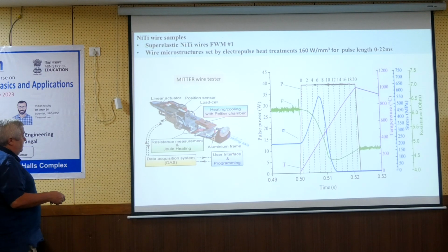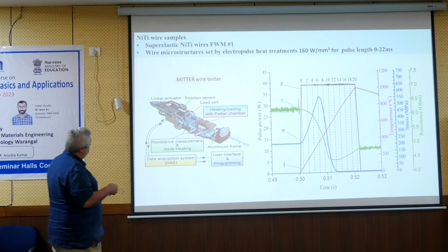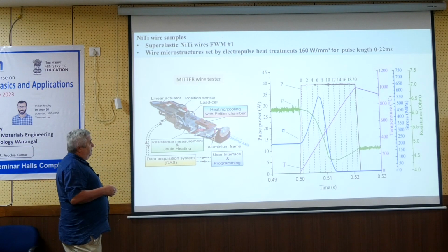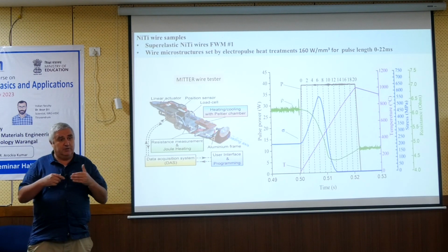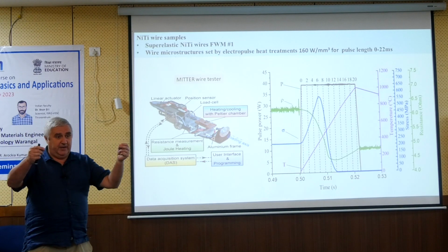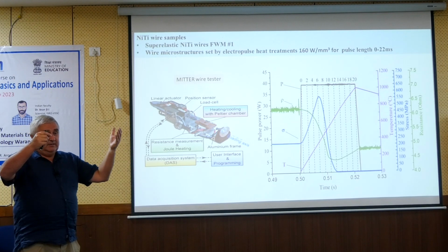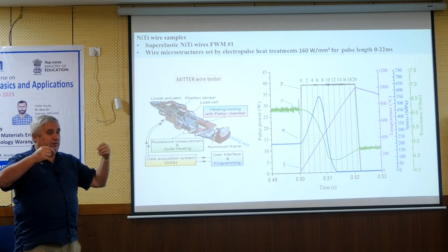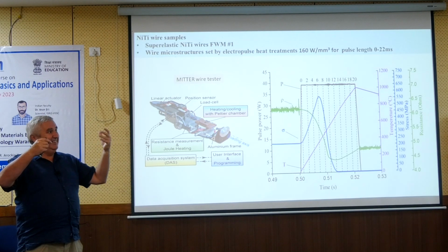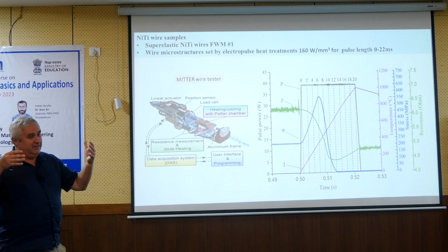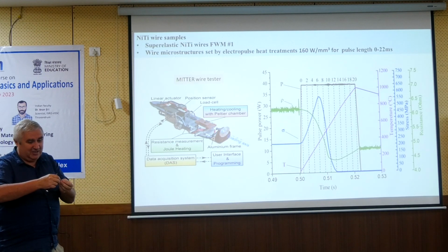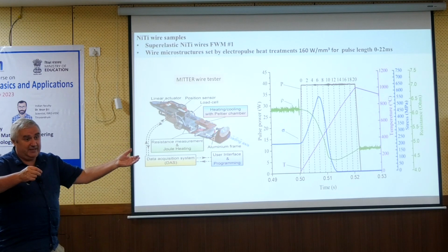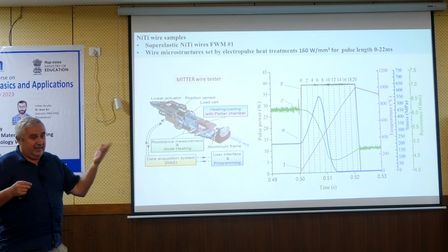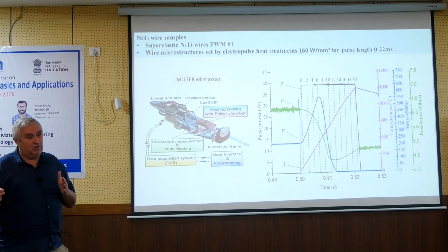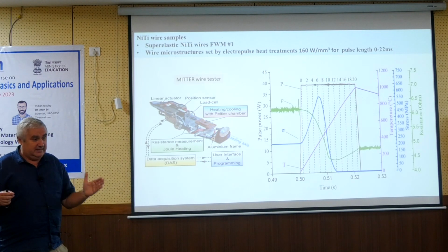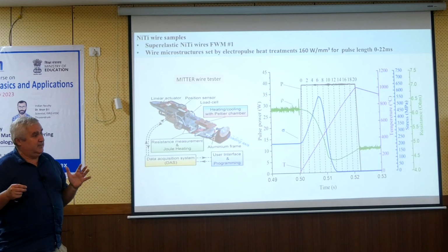It has one advantage: the grips are non-conductive, so we can measure the electric resistance, but we can also use it to perform heat treatment by Joule heating. If you put the wire into the furnace, you put it at typically 500 Celsius for 10 minutes. This is convenient in metallurgy, but with nitinol sometimes the process occurs already when you put the sample into a furnace that is already preheated. So when you are heating the wire, it occurs. If you do it next time a little bit slower, the wire is different. If you want exactly the same wire with exactly the same microstructure and properties, heating in a furnace is not always ideal.